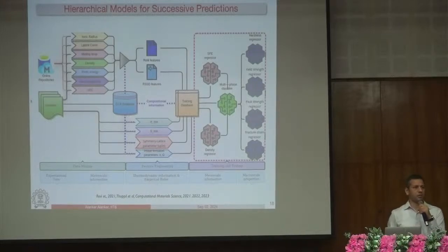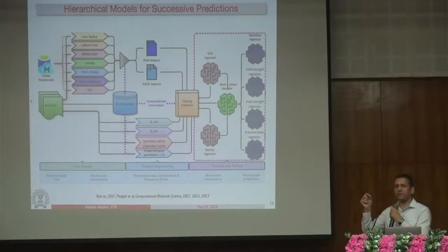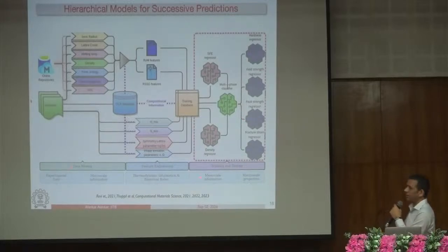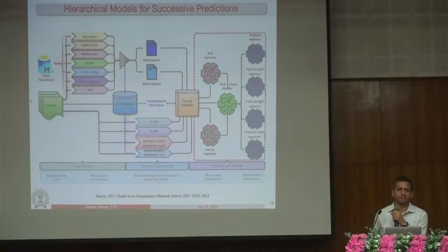It has correlation with the modulus of elasticity. Right. So these two properties we calculated, and then based on that, we created several independent regressors, and those regressors could predict hardness, which is a very important engineering property, yield strength, peak strength, fracture strength. Right. This was done over multiple length scales, as you can see, because some of the properties are mesoscale and microscale properties, and some of the properties are macroscale properties.